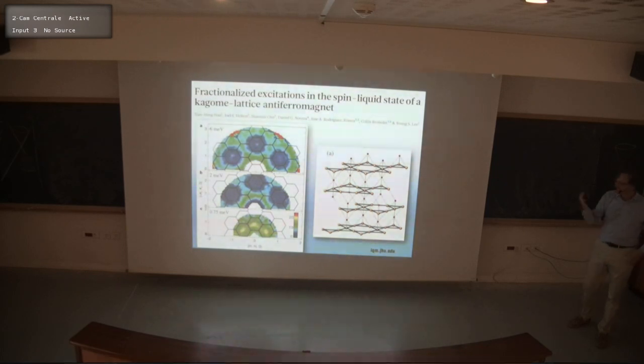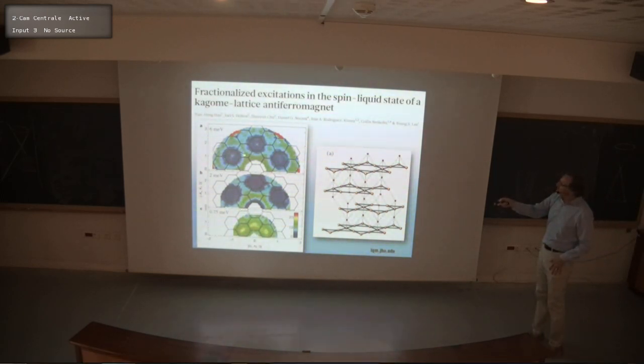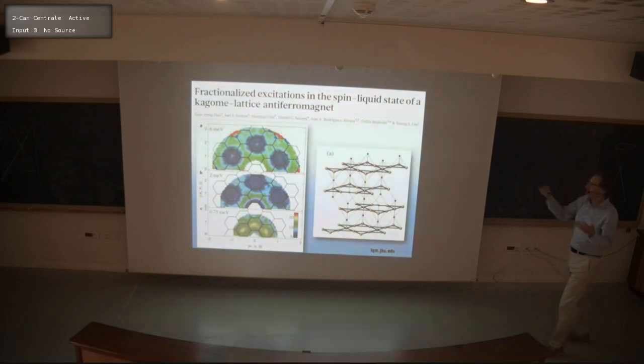So it's a little kind of weird, but it turned out that the instrument was very well suited for this experiment. And what's unusual is that this is the Brillouin Zone, these honeycomb regions. So in a system that would have long-range magnetic order, spin wave excitations, etc., you would basically have dispersion relations emanating from magnetic reciprocal lattice points, and there would be little rings as you come up in frequency, little rings that would replicate in each Brillouin Zone. And then you'd find your dispersion relation, etc.